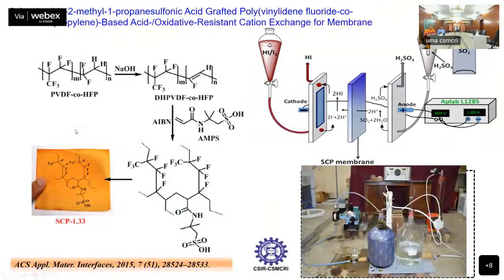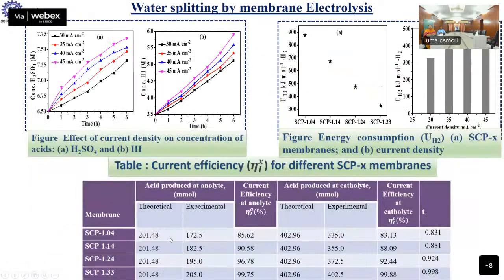This is the actual indigenous membrane we developed from PVDF. It is commercially available. First it was treated with NaOH, and then double bonds were generated. Then acrylamido propane sulfonic acid was grafted onto it, and the membrane was cast on a glass plate. Depending on grafting density, this membrane shows good performance, and it was used for the reaction at different current densities. At each current density, how much acid has been developed has been calculated, and also the current efficiency and the anolyte and catholyte side reactions have been calculated.